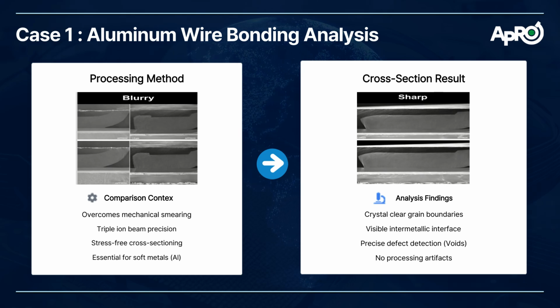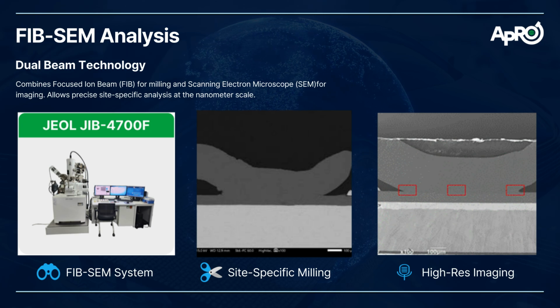In our aluminum wire bonding analysis case, Triple ion beam precision milling clearly shows grain boundaries and intermetallic compound interfaces with accurate void detection. FIB-SEM is a dual-beam technology combining focused ion beam and scanning electron microscope, enabling nanometer-level precise analysis. It offers site-specific milling, high-resolution imaging, and 3D tomography.